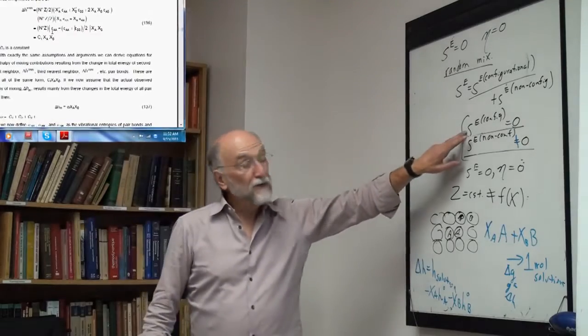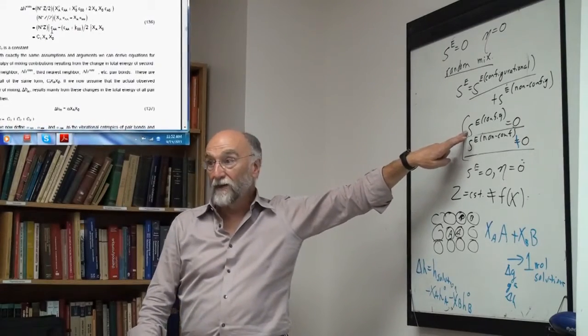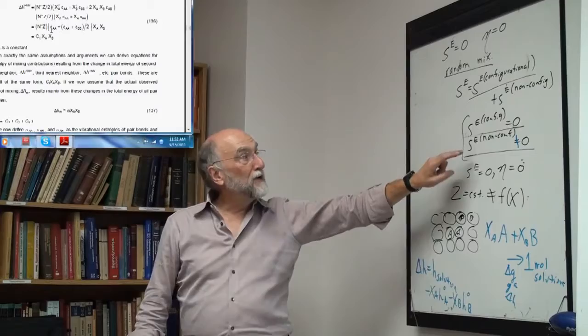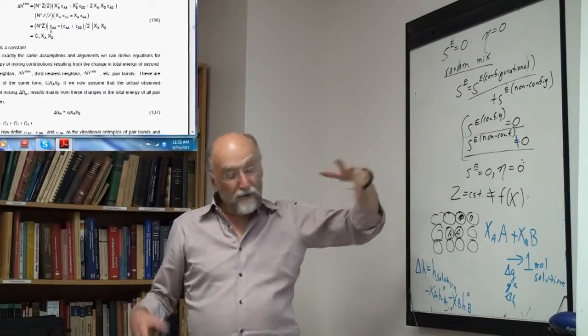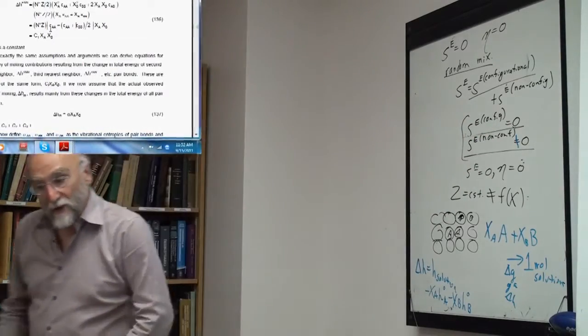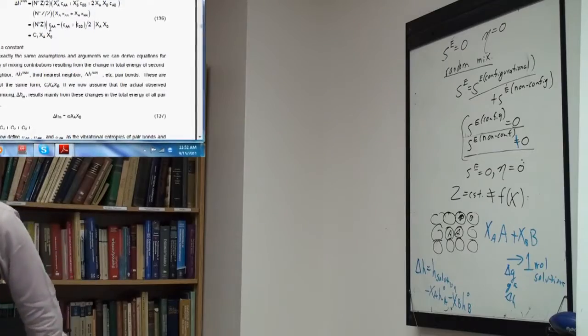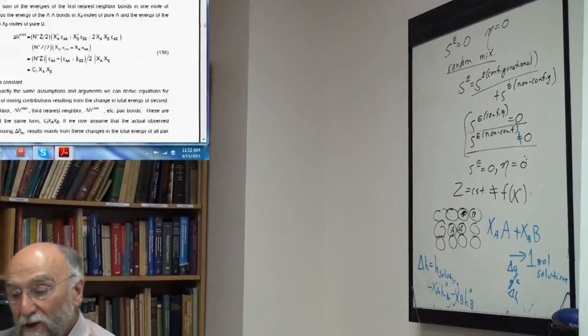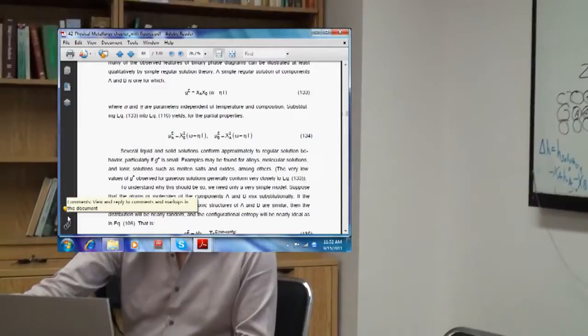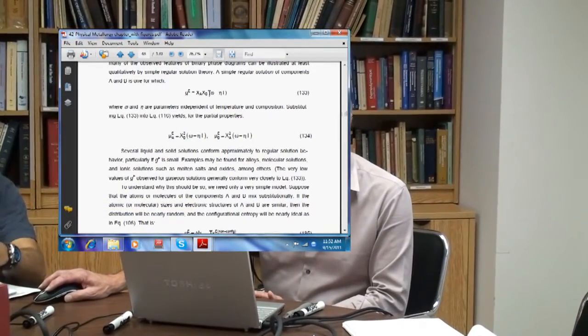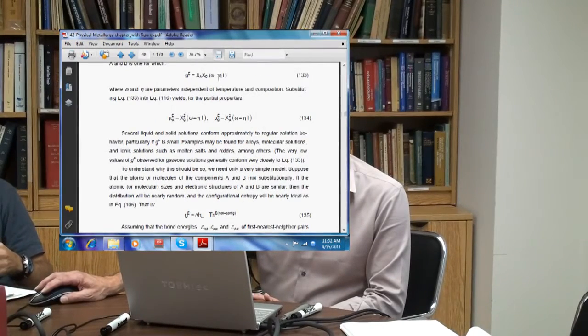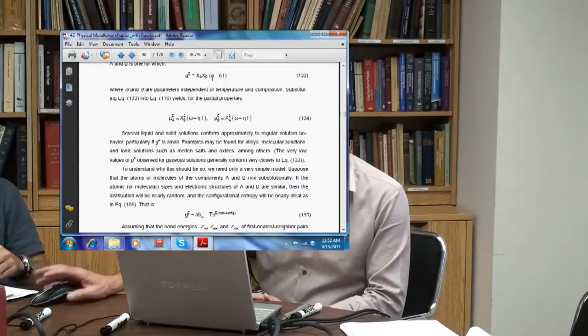So this is not a bad assumption unless you get too far off, and then it starts to become a bad assumption. But even if S excess is not zero, the system is still pretty close to a random mixture. So you can show in the quasi-chemical model that as this omega minus A to T term deviates from zero, the A to T term at the beginning is much less important than the omega term. It's only later on that it starts to get bigger.